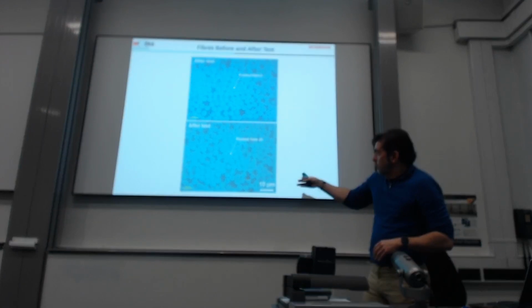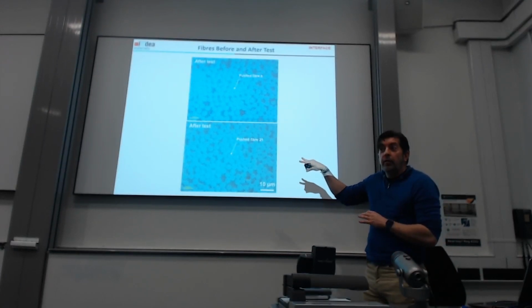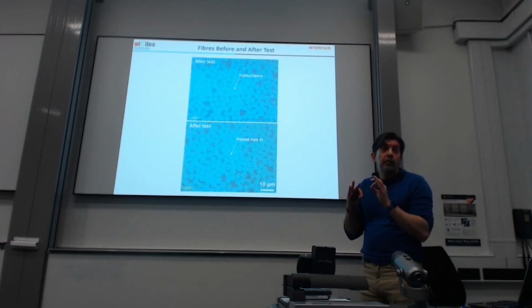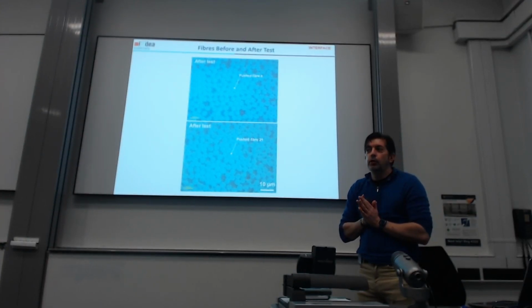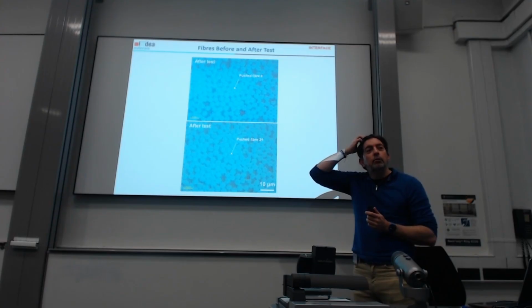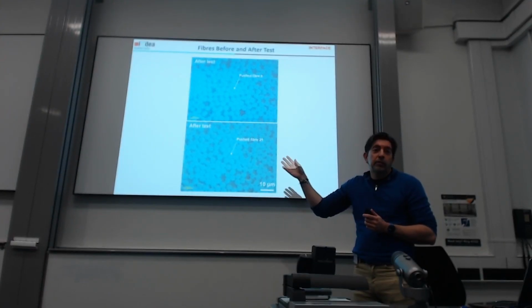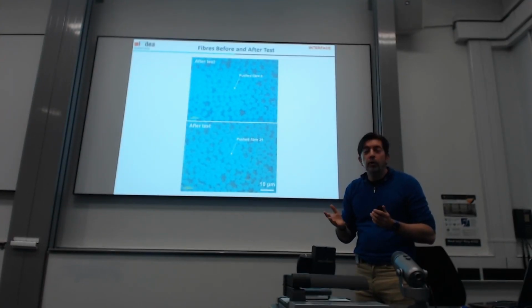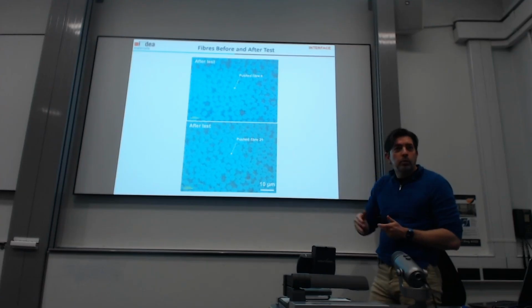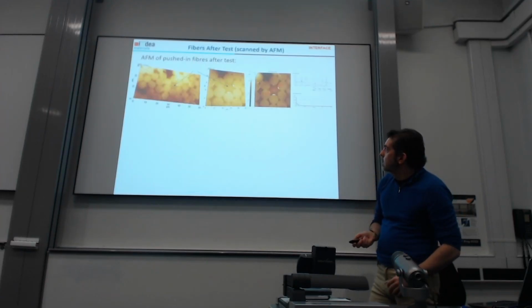Of course, in this case, I have a lot of fibers to choose from. Sometimes the volumetric fraction of the fibers is not as you expect. This is maybe a 50, 60% volumetric fraction. If you have fewer fibers, it is more difficult. But normally you have enough to go around and do this test.